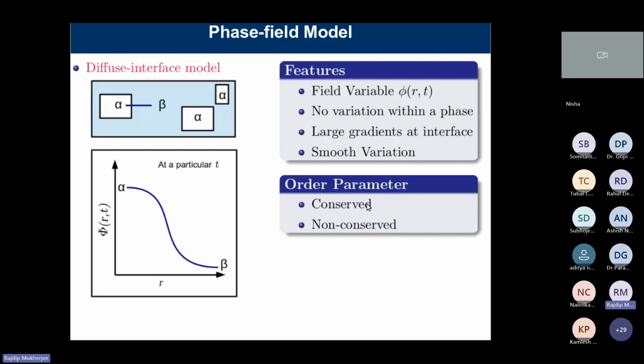If you have grain growth, or an order-disorder transformation, like a magnetic domain where some regions are ordered and some are disordered, we use a non-conserved field parameter. What is a conserved field parameter? If we start with an alloy that decomposes into two phases, the average composition of the alloy remains the same. If you add all the composition and average it out, it remains the same. For a non-conserved field variable, like solidification from liquid to solid, all the liquid will ultimately transform into solid, so one of the field variables will disappear from the system. So there are different kinds of field variables with which we describe the microstructure.